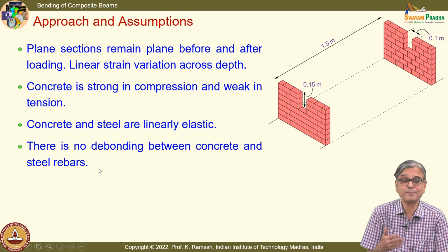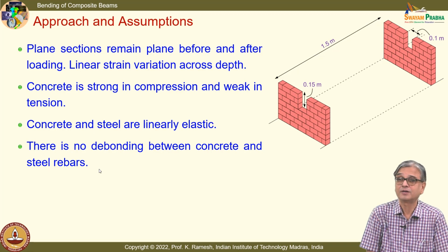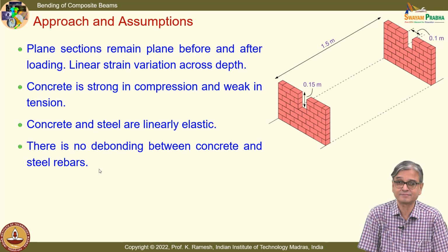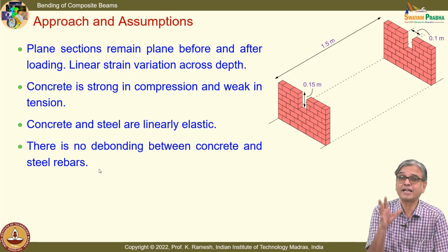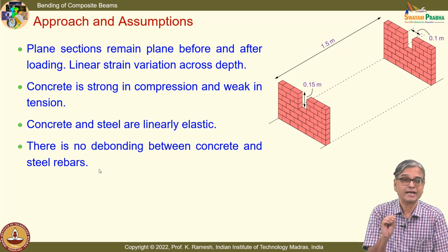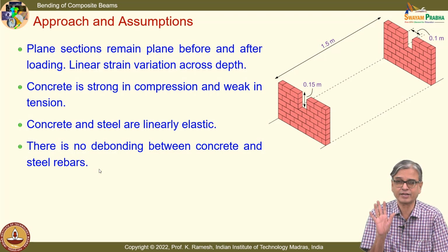See, it may so happen when you construct the beam, it may be like this, but if you have not taken care of water seepage into the system, you may find that steel will corrode and it will increase in volume, and you will have debonding occurs between the steel and the concrete.